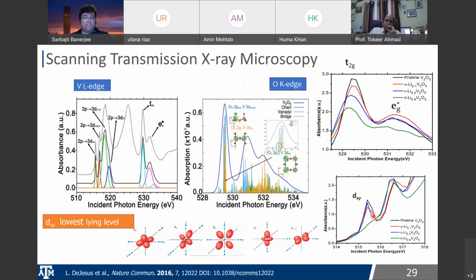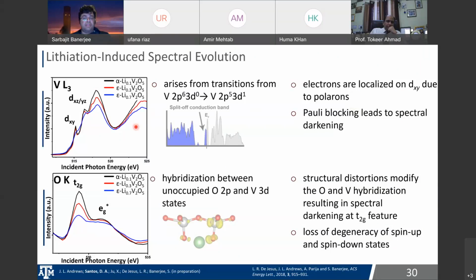And so we can calibrate this. And also as this happens, this is the vanadium L3 edge, where we're looking at transitions from vanadium 2p to vanadium d states. And then at the oxygen K edge, we're looking at transitions from oxygen 1s to oxygen 2p, but the oxygen 2p is hybridized with vanadium 3d, and we can see this crystal field splitting, the t2g and eg star. And what ends up happening as we lithiate, the t2g peaks are becoming weaker, right? And so you can sort of see this a little bit more clearly here. As lithiation happens, these dxy states get filled, and the t2g intensity steadily decreases.